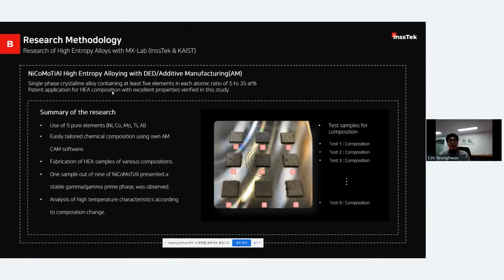The second paper is written by KAIST and InssTek. This research was developing a new high-entropy alloy with nickel, cobalt, molybdenum, titanium, and aluminum. By software simulation, target compositions were designed. Each of the 5 pure element powders was supplied in powder feeder independently. After that, test was conducted with changing compositions while 3D printing. As in the picture, 9 different composition samples were made by one click. In one sample from the 9 samples, stable gamma prime phase was discovered. This new material was applied for a patent.